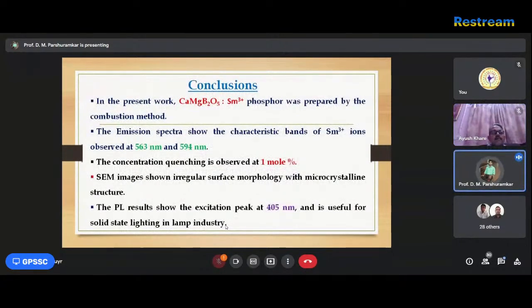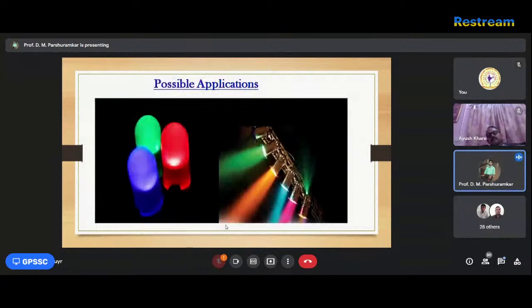The conclusion is that in our present research work, we prepared the CaMgB2O5 Sm3+ phosphor by the combustion method, which is very simple to follow. The emission spectra show the characteristic bands of the Sm3+ ion observed at 563 nanometer and 594 nanometer. The concentration quenching is observed at 1 mole percent, meaning we have to choose 1 mole percent for future work. The image shown here has an irregular surface morphology with a microcrystalline structure, and the PL result shows the excitation peak at 405 nanometer, which is useful for the solid state lighting industry. These are the possible applications of this research work, used for different LED applications.